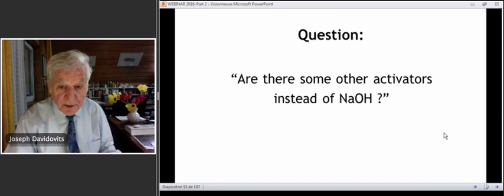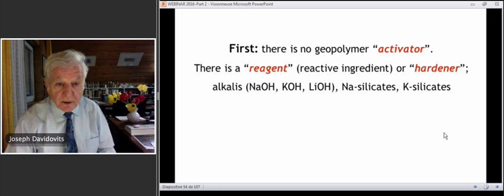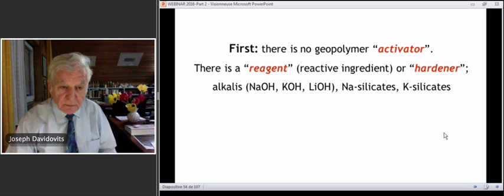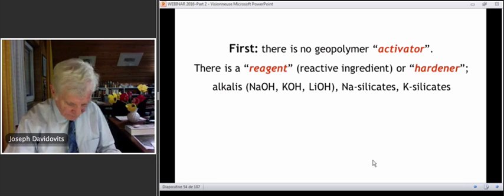I had this question: are there some other activators instead of NaOH? My answer is the following. First, there is no geopolymer activator. We have a reagent, reactive ingredient, or hardener, that involves sodium silicates, in which we have added previously NaOH and KOH. We come back later, because these are sodium silicates or potassium silicates. There's no free alkali in it. So we don't have any activator.